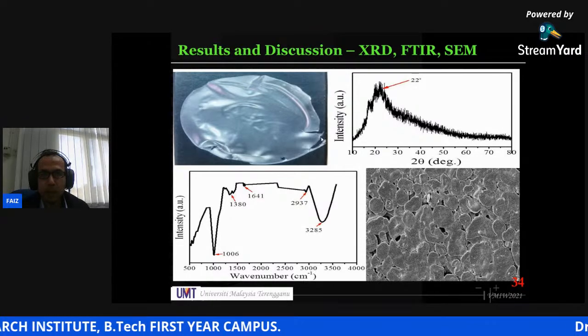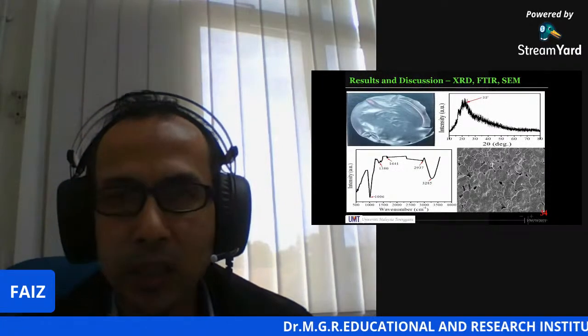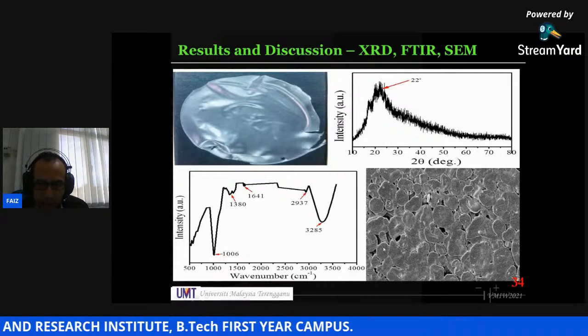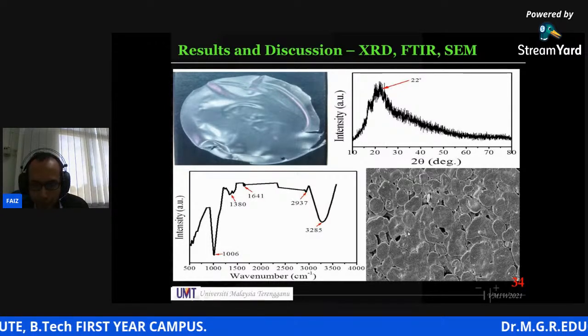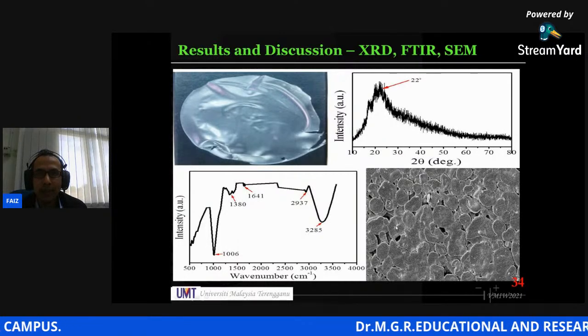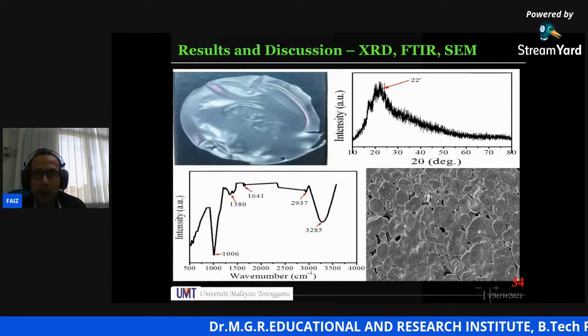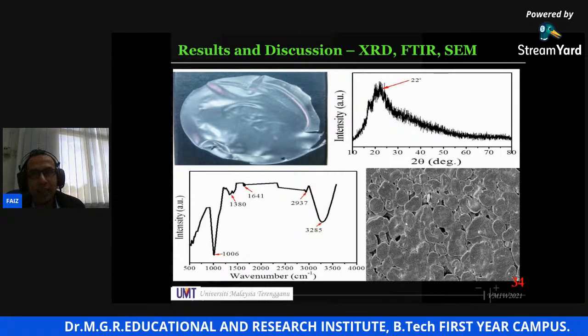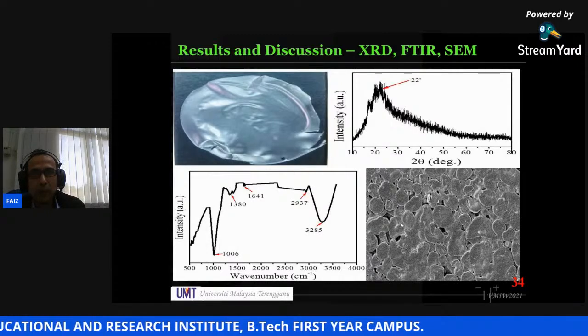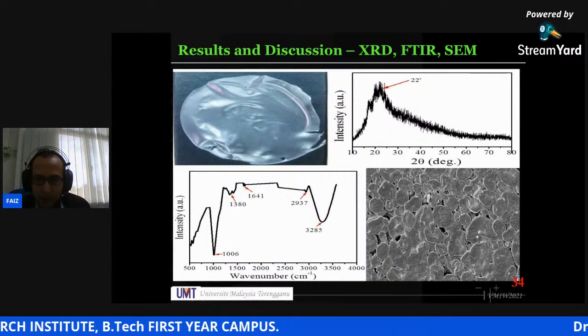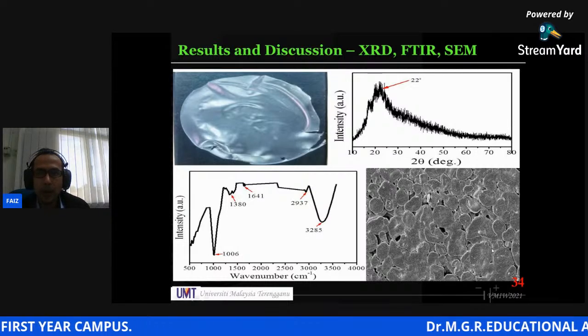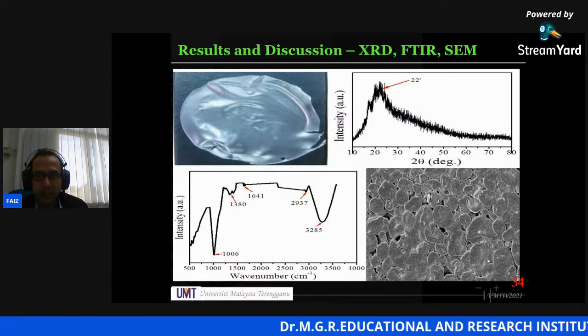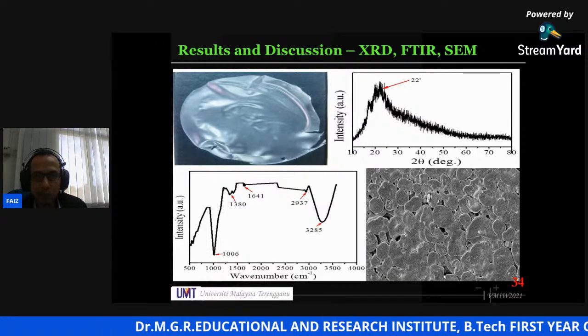So we have the SEM image of the film. Okay, the film has some agglomerated surface with a circular shape, then became flat, joined each other, and some pore structure obviously appears in specific areas of the samples. So we also calculated the pore size, which was estimated to be in a diameter of 20 to 70 nanometer, and this interesting property is thought to contribute to enhancing the electrical property of the films.